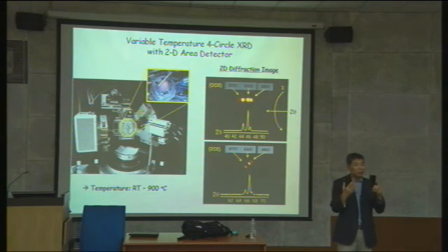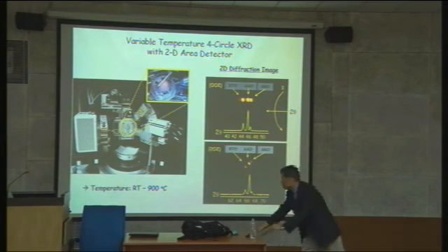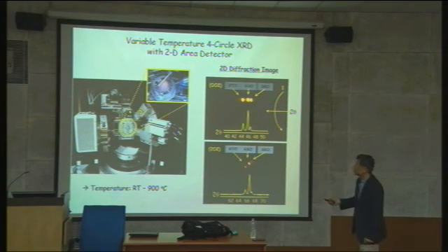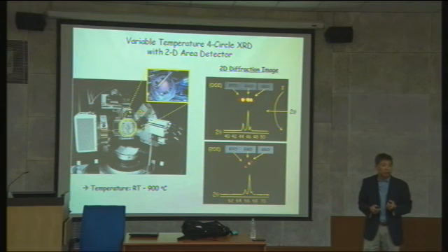It is very challenging initially, especially for low symmetry material systems, but you can determine the epitaxy arrangement, in plane and out of plane, your strain information, coherent or incoherent, and how good the crystalline quality is from the rocking curve. You have a lot of information you can get. This thin film geometry allows you to access the different orientations and epitaxy of thin films.